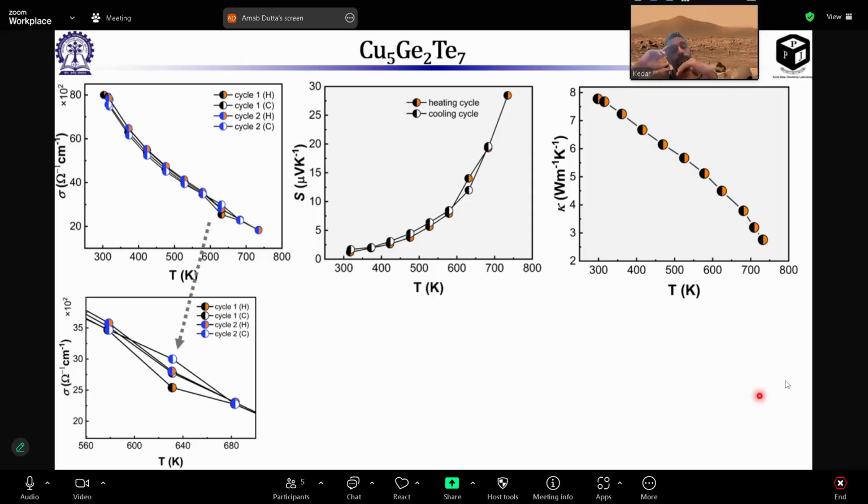It's very hard to go below the amorphous limit. So something else is going on then. The Lorentz number is changing. There's some interesting physics in the system, right? Because it's unlikely that your total thermal conductivity goes that low. So that means the Lorentz formula is not correct.